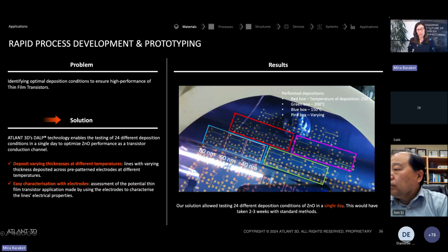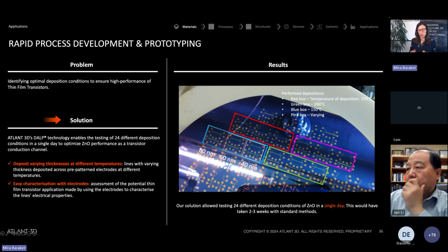And here is an example about rapid process development and prototyping. This is the case of high-performance thin-film transistors. So we have pre-deposited contacts on the surface, and what we have done with our technology is that we were able to deposit zinc oxide with different deposition conditions, and now you have a readily available wafer with multiple prototypes of different materials or different material conditions of the transistor.